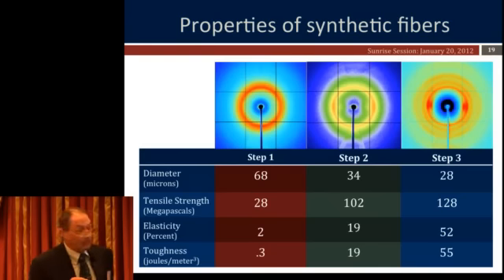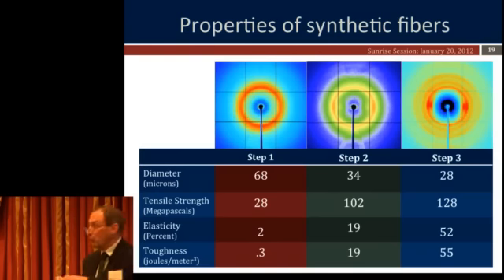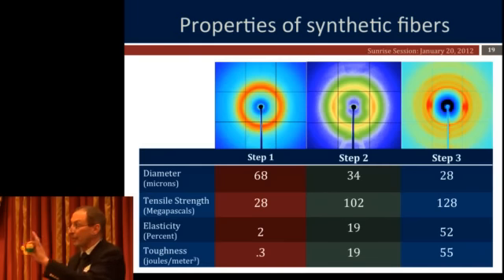All right? Now, if you put it in the alcohol water bath and stretch it, you see that the diameter shrinks, you get a very large increase in tensile strength, a pretty large increase in elasticity, and the toughness jumps up. And what you can see, not very well, is you start to see multiple rings, which starts to indicate structure. So what we know, in examining those rings, is that we made the Legos. So what happened here is there were no Legos. But once we put it in the alcohol water bath and stretched it, the Legos formed.